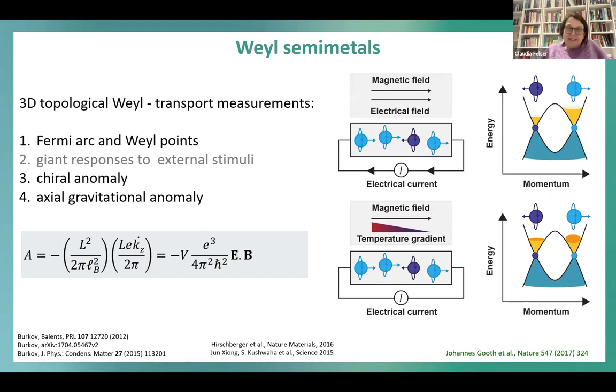So the next slide now hopefully shows this in relation exactly. So now we have our Weyl semi-metal and this E dot B term. I think we can ignore it, but this is exactly what we want to do. You see here in the middle, at the right side, you see the Weyl semi-metals and the nice case where you have the asymmetry between the violet electrons and the bluish electrons. In the middle, you see the experiment. You have simply to do an experiment with a magnetic field and the electric current. So you simply measure the conductivity of this material, then you can prove this chiral anomaly.